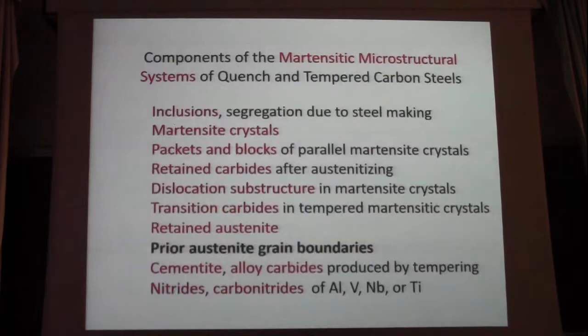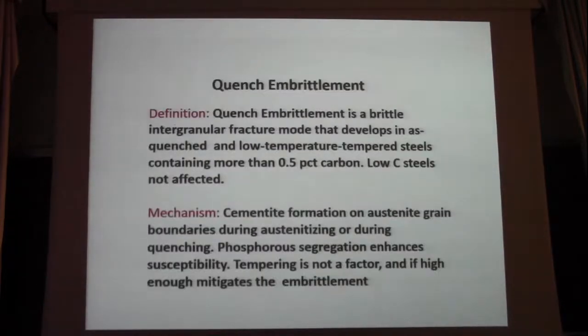Okay, I guess I have to move ahead a little bit. The mechanism is cementite formation on austenite grain boundaries during austenitizing. But during quenching, phosphorus segregation enhances it, but doesn't cause it. Okay, moving along here, mechanism. Now, on these intergranular fracture surfaces, you hardly see anything. Smooth fracture. What's happening here? Well, cementite formation, carbide formation happens because austenite grain boundaries are rough. Where crystal structures join, they are preferred nucleation sites for carbides, and cementite forms.